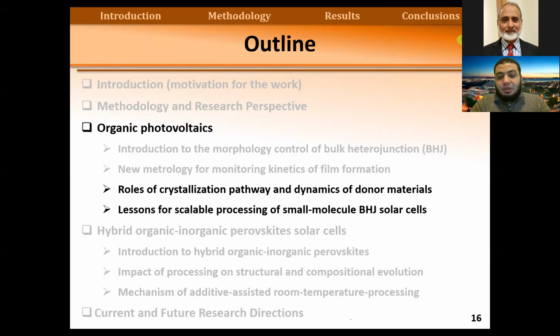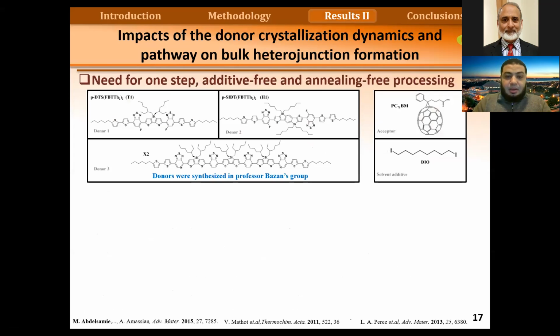So now we move to a different topic. In the previous topic, we were applying a new technique to different processing conditions. But for this one, we will try to understand how the design of the molecule affects its self-assembly and how it affects the film formation. We use small molecules as a donor material, and we use PCBM as an acceptor material. We started with a material called T1, which is a small molecule, and we tried to vary the backbone of the material. We changed the units here and tried to understand the effect of this molecular design on the film formation and on the final product.